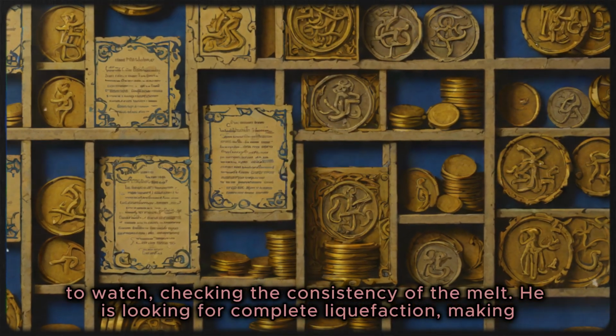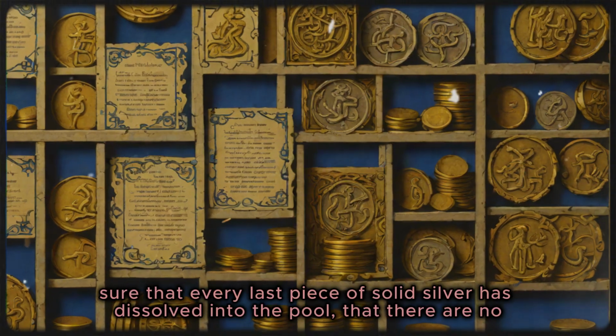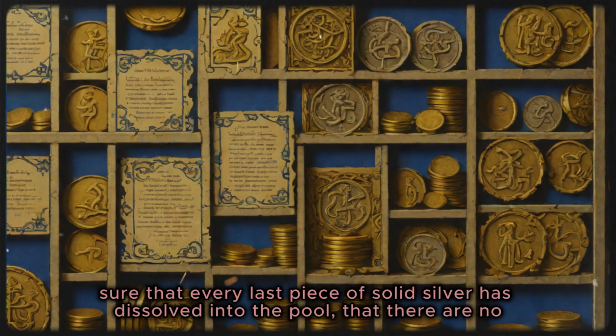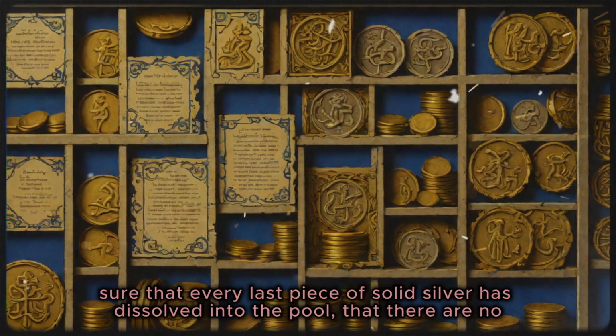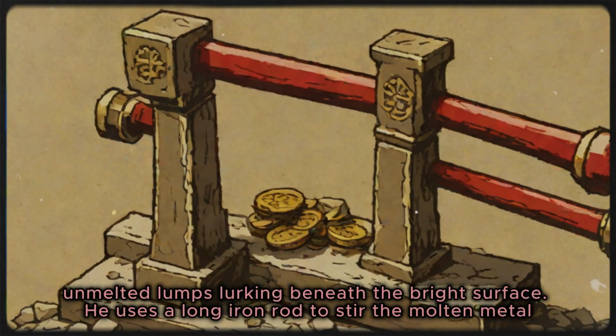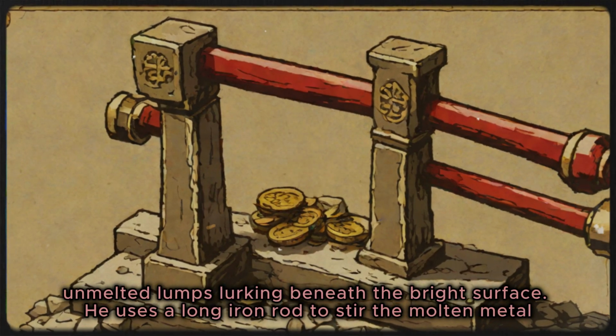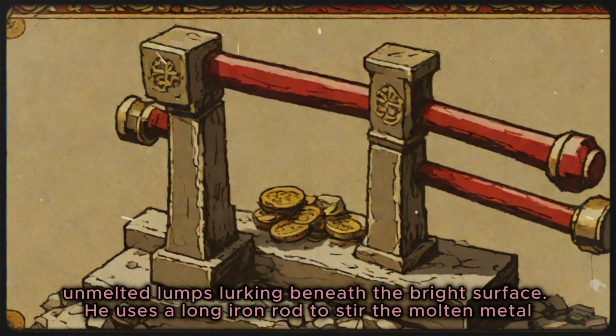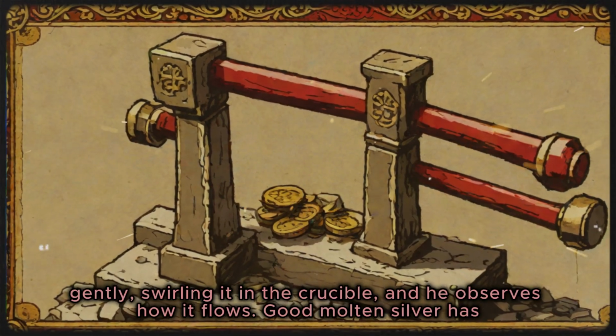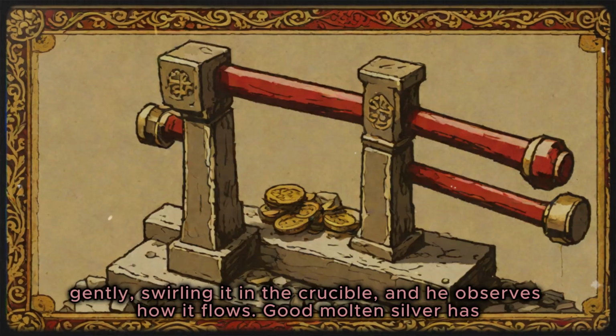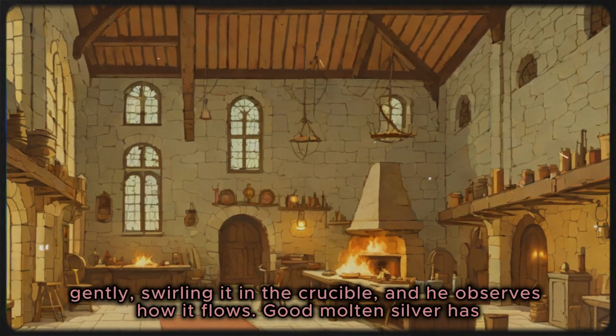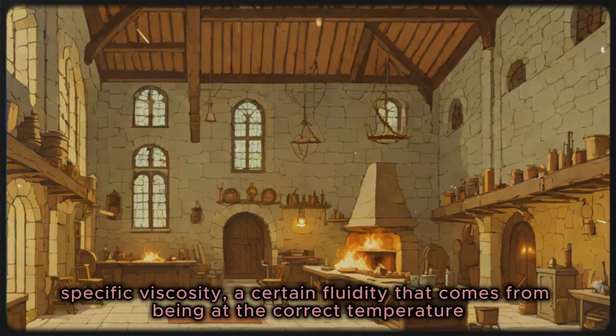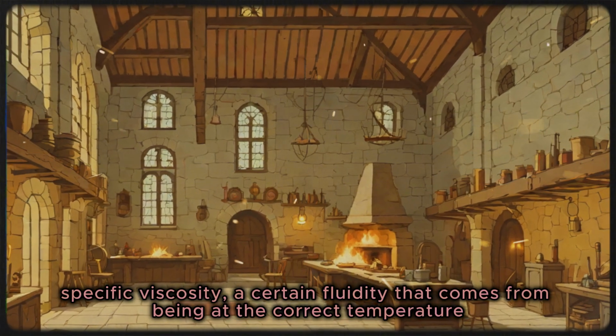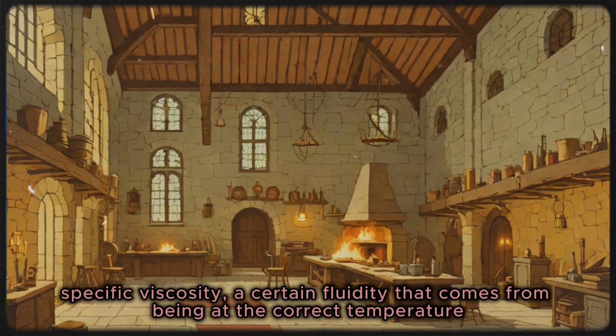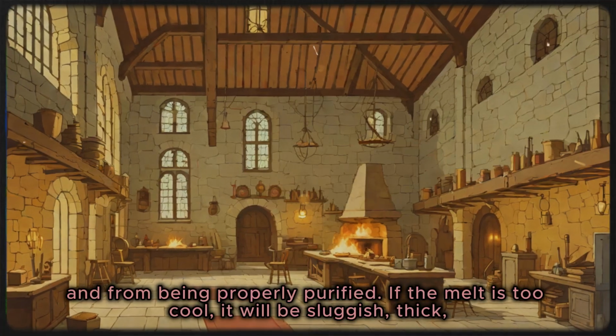He is looking for complete liquefaction, making sure that every last piece of solid silver has dissolved into the pool, that there are no unmelted lumps lurking beneath the bright surface. He uses a long iron rod to stir the molten metal gently, swirling it in the crucible, and he observes how it flows. Good molten silver has a specific viscosity, a certain fluidity that comes from being at the correct temperature and from being properly purified.